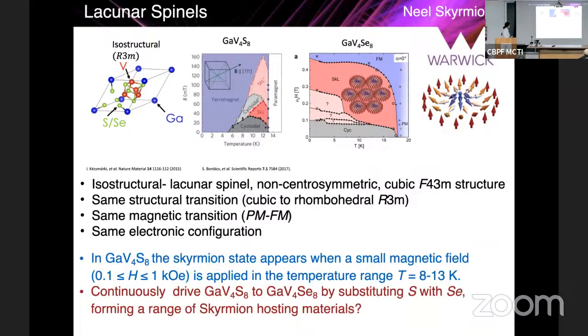Now, I've plotted the HT phase diagram taken from literature. These are very well studied. And you see here the skyrmion lattice, the skyrmion pocket, is very easily identified in these materials. And here again, they are in a certain range in the HT phase diagram. So what we wanted to see was, since we have the gallium vanadium four sulfide and the selenide, both known to exhibit skyrmions, is it possible to go all the way from gallium vanadium four sulfide to the selenide by gradually substituting at either the sulfur site or the selenium site, and therefore create a whole range of skyrmion exhibiting materials?